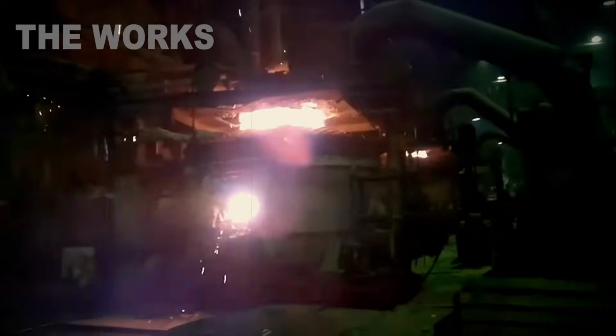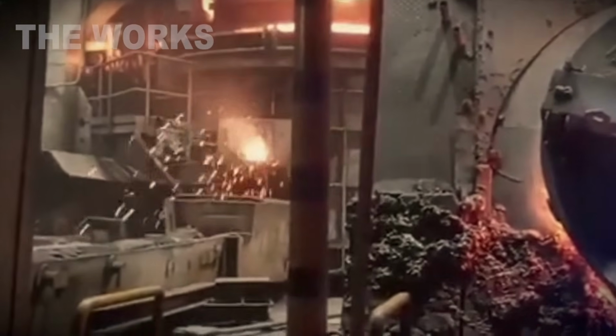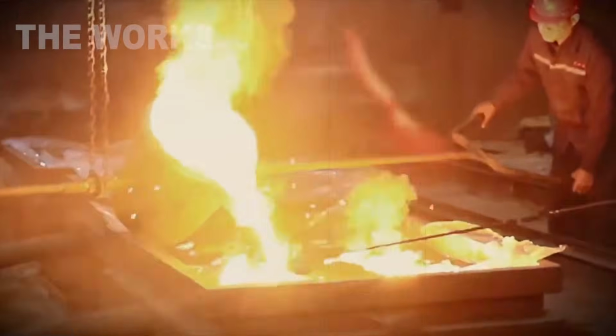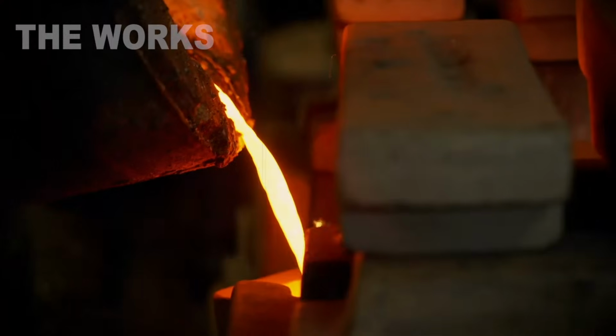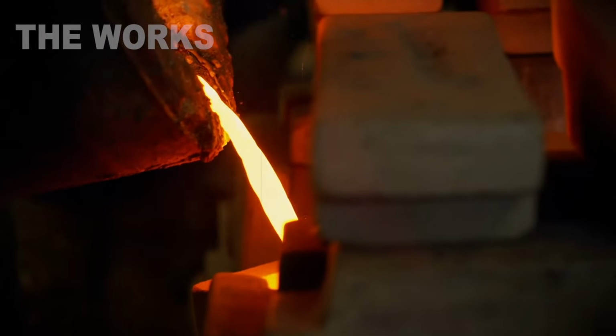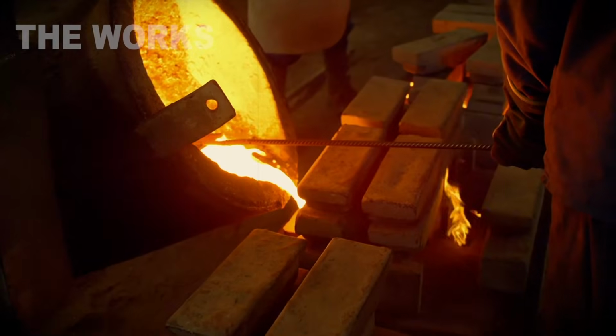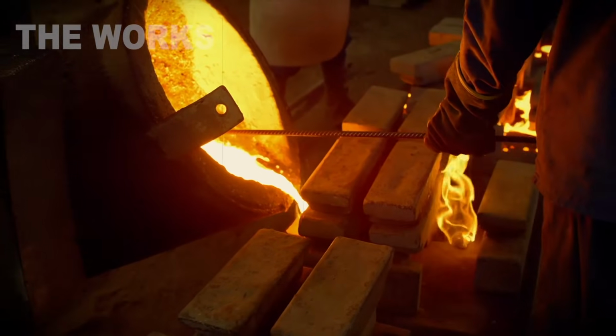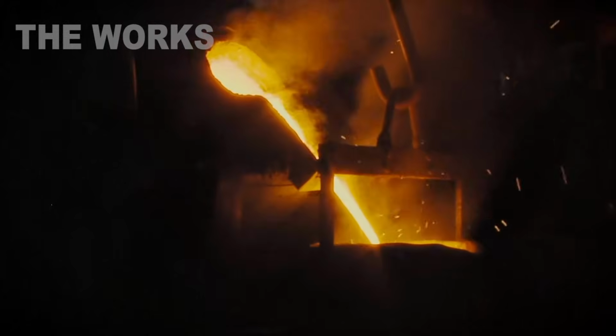Then the metal is stirred in an argon-oxygen decarburizer. Argon blown in from below. Pressure: 73 psi. Flow rate: 79 gallons per minute. Argon bubbles rise. Mix the melt. Carry gases to the surface. Hydrogen content drops from 10 to 2 parts per million. Oxygen from 80 to 20. Low gas content is critical. Gas bubbles become cracks. Finished steel pours into a ladle.